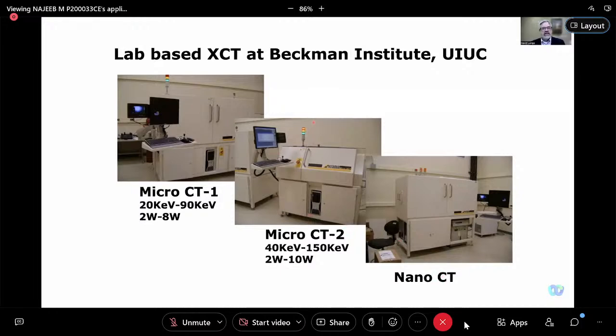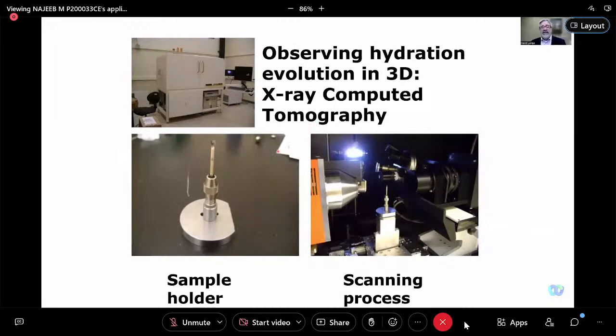Here are some pictures of how we ran this experiment. First, to the uninformed, you're using really, really small samples. On the lower left, the little chip of material is our sample holder. We put that into the configuration on the right, where the X-ray source comes from the left of the photograph toward a sensor on the right. The other important thing is that your stage rotates. Any one position is just like an X-ray, so you're getting a shadowgram of your sample. Then you move it a degree or two, take another picture, and it rotates around 180 degrees, getting every angle.